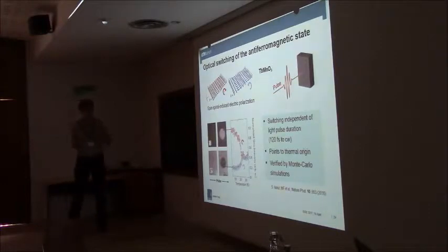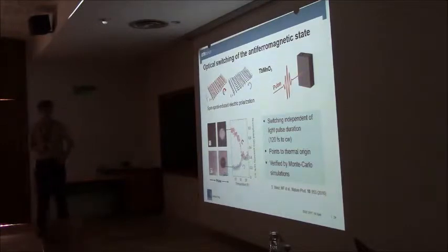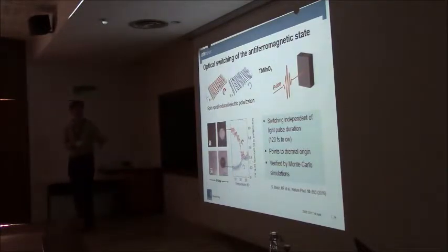So it's nothing fancy, it's a heat effect, because you can do the same with a femtosecond laser, nanosecond laser, or with a laser that's always on, so a helium-neon laser. So it's independent of all that, it's just the intensity, only the incident energy that lets this switch. And that very strongly points to a thermal origin.